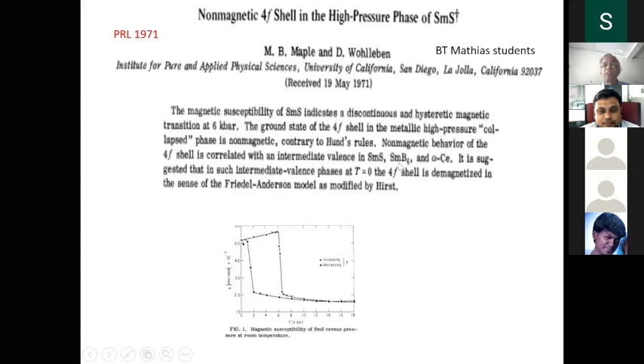They behave exactly the same way. The idea of the intermediate phase is that the electrons get delocalized from the core, and then come back to the core shell. It keeps fluctuating between the local orbital and the conduction band. With time, it undergoes this even at T equal to 0. It's called quantum zero-point motion. The term "intermediate valence" was coined by the authors here.